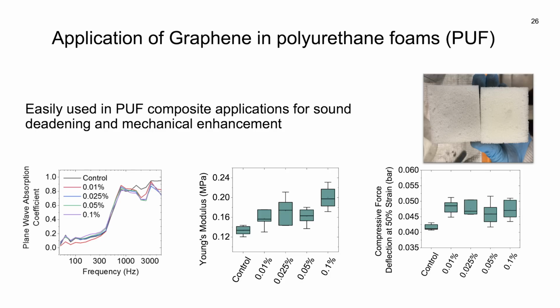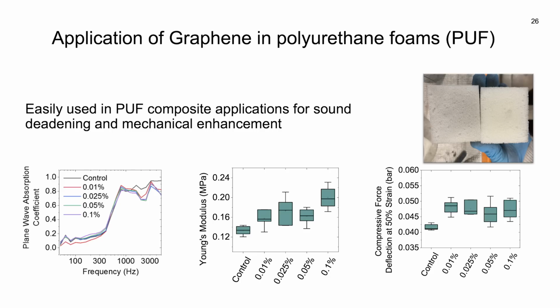So they put it into their foam cushion seats. It did everything that it was supposed to do. It increased the modulus, it increased the compressive strength, and it had a better coefficient of sound absorption. You can see the foam cushion seat is a little bit darkened with the graphene versus the virgin foam. So I said, give me that foam cushion seat, send it back to me. We got the foam cushion seat. Guess what we did with it? Turned it into flash graphene. And so you see now the life cycle. You can just take old vehicles, turn them into material for new vehicles, and just keep going back around.